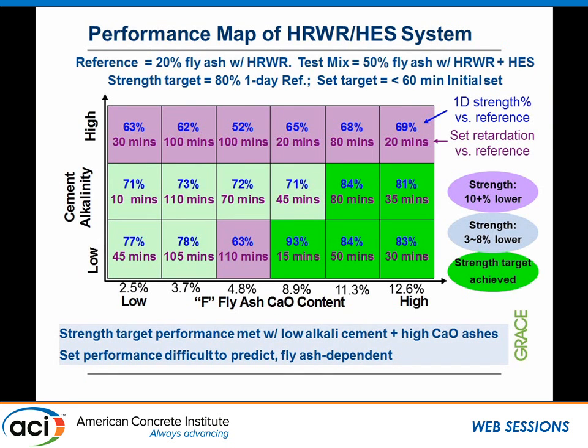So one word to think about, there are all these different interactions between the cement, the fly ash, the admixtures. So when we tried this type of admixture with 3 different cements that have different alkali content, and also 6 different fly ash that has different calcium content, we can see that there are differences. What we are checking is really 1 day strength versus reference, and also the set time versus reference. Our target is really to have strength to be 80% at 1 day of the reference, and less than 1 hour for the initial set.